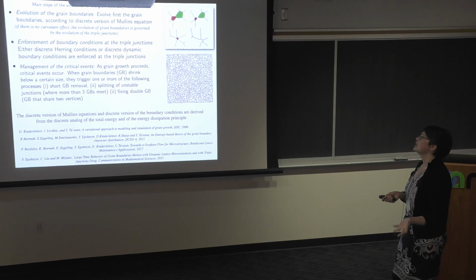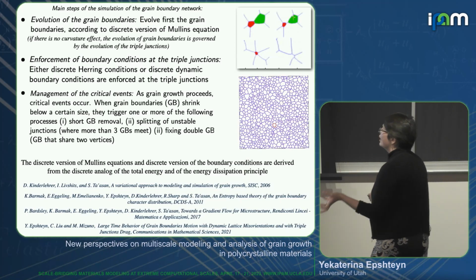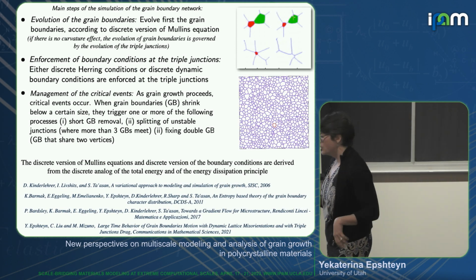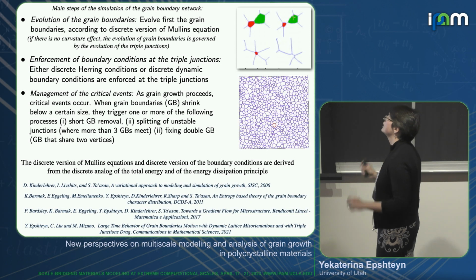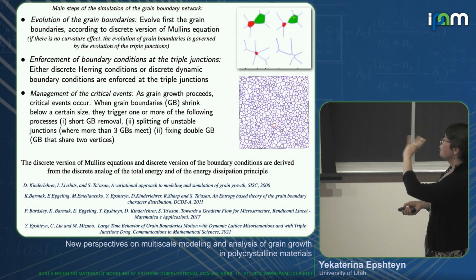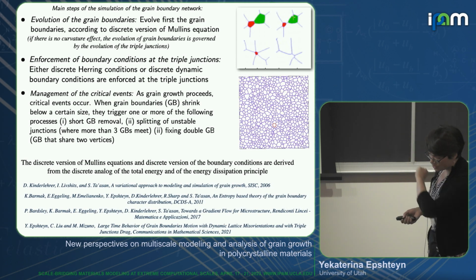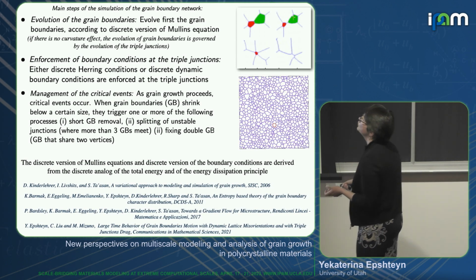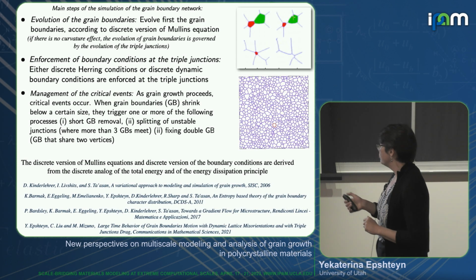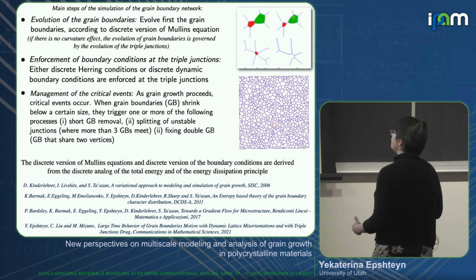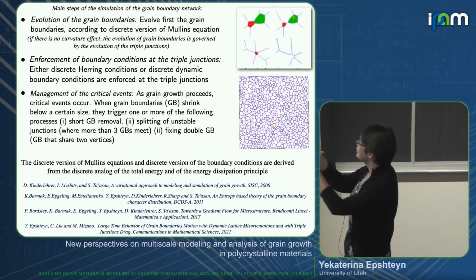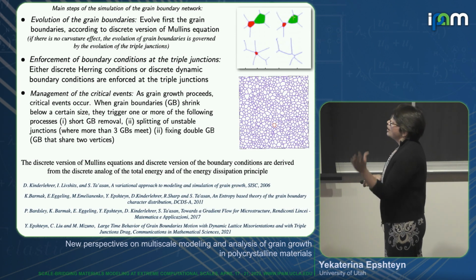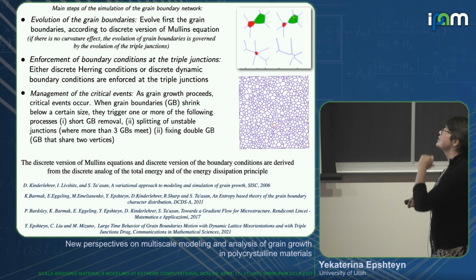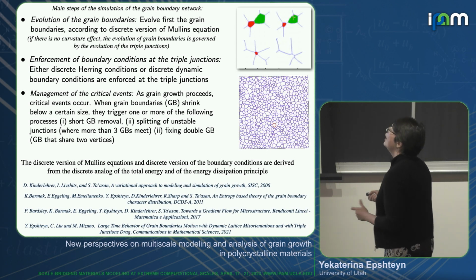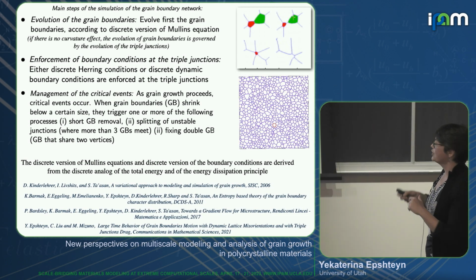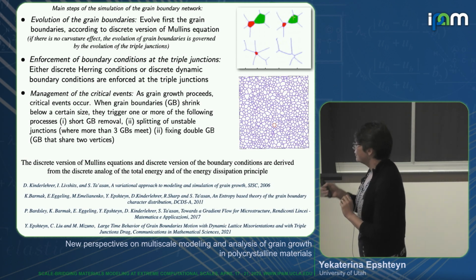And once we have some confidence in our model, I will mention a little bit about numerical simulations. We have numerical simulations that are based on the full model that takes into account dynamics of grain boundaries, dynamics of triple junctions, dynamics of misorientations, and also we have simulations of the reduced model. I'm not going to go into technical details of how these simulations are developed, but our grain growth simulations are based on a sharp interface approach. So we model grain boundaries explicitly, and we model topological events explicitly, which is computationally much more expensive, but it allows us to separate different relaxation timescales and understand better the effect of different relaxation timescales.